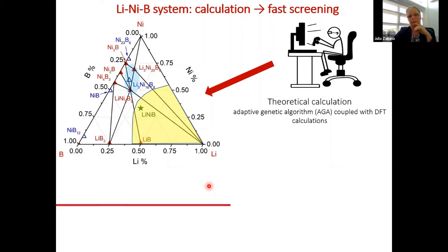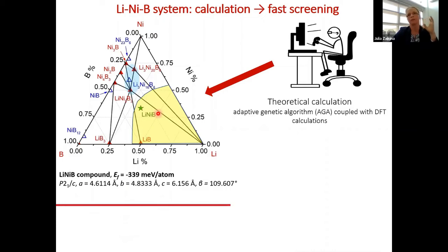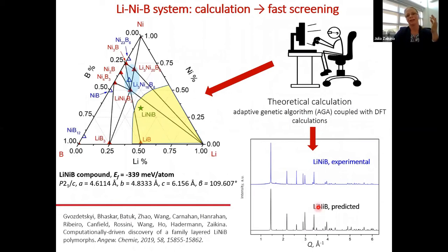So we use our collaborations with theoretical chemists, and they, by using an adaptive genetic algorithm coupled with DFT calculations, predicted the equimolar ternary compound, lithium-nickel boride. They not only predicted this composition to be stable, but they also gave us an idea about the structure that compound might have. And to our greatest surprise, we tried in the lab and obtained the powder pattern, which is in close resemblance with the predicted one. Yeah, so this is really a remarkable way of discovering new compounds. We knew its structure before we made it in the lab.